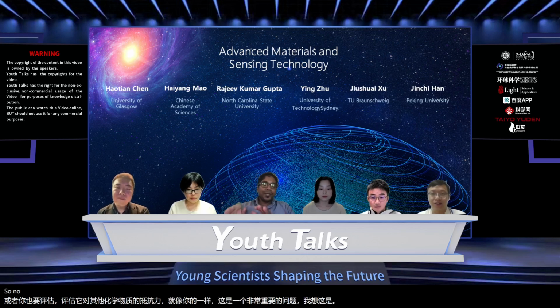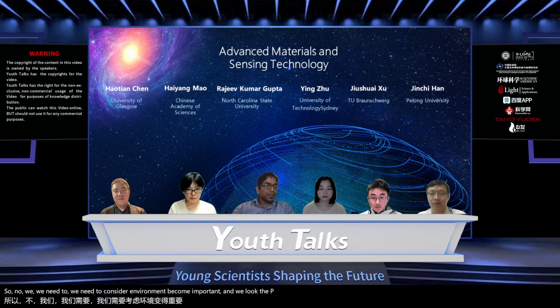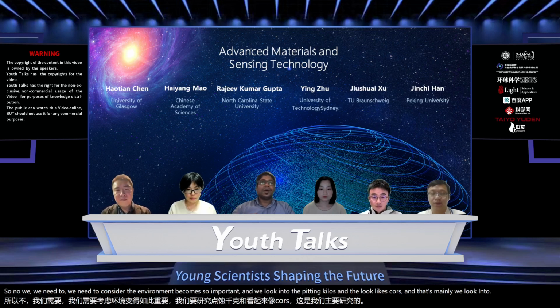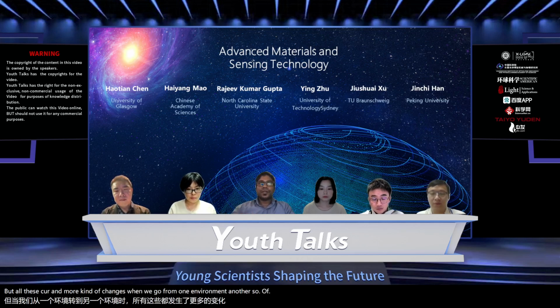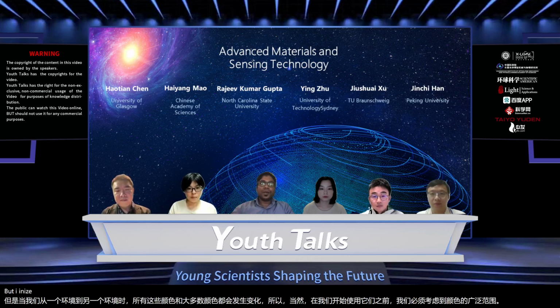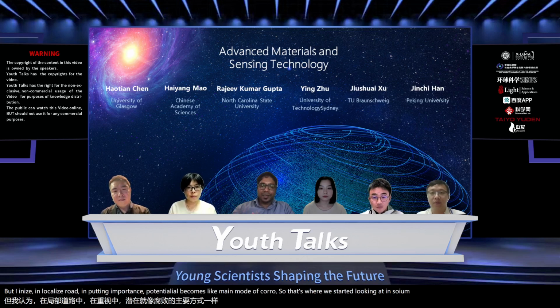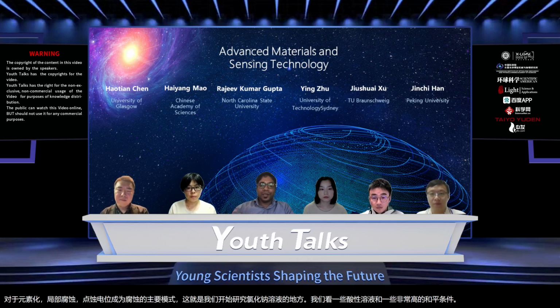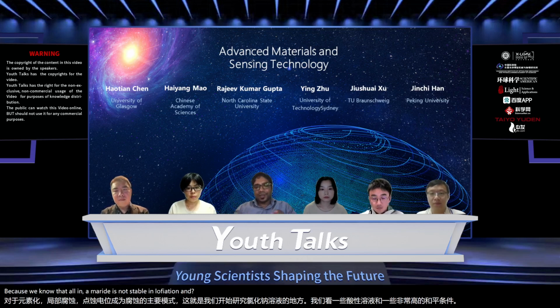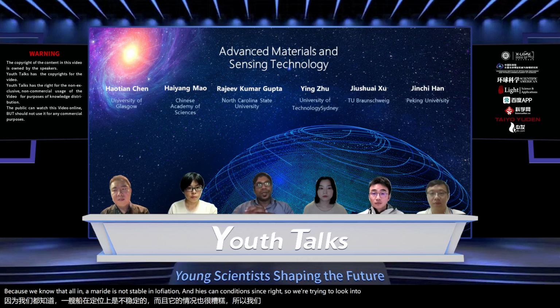So we need to consider the environment, which becomes so important, and we looked into pitting corrosion, the localized corrosion. That's mainly what we looked into, but all these corrosion modes change when we go from one environment to another. So of course, before we start using them, we have to look at a wide range of corrosion. For aluminum alloys, localized corrosion and pitting potential become the main mode of corrosion. So that's where we started, looking at the sodium chloride solution. We looked at some acidic solutions and some really high pH conditions, because we know that aluminum oxide is not stable at low pH and high pH, right? So we're trying to look into those conditions, whether these alloys could give really good corrosion resistance.